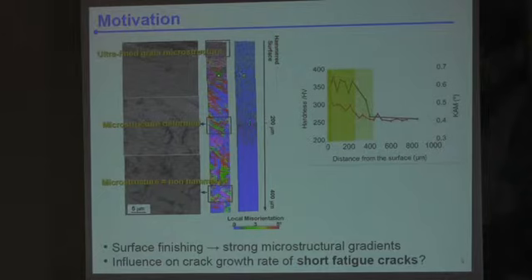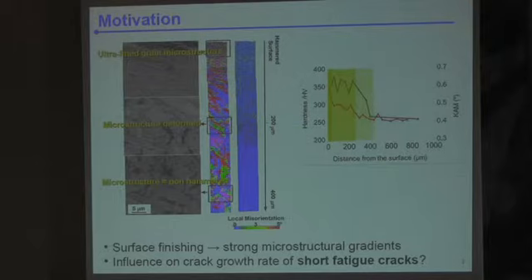And of course this has an impact on the surface hardness, which falls off quite quickly, but it falls off to a bulk level after, say, 0.5 millimeter. So the surface finishing has indeed a large influence on the microstructure. And then the question we wanted to address was, okay, we have a surface gradient. How can this affect the propagation of the fatigue cracks if they're small, right? Is this gradient large enough to have an effect on it?